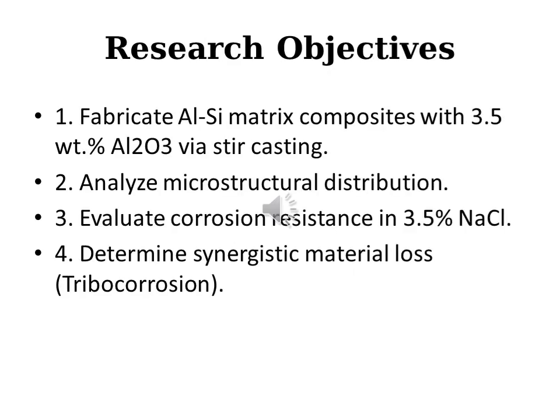Our research objectives are fourfold. First, fabricate these aluminum silicon matrix composites using the stir casting method. Second, to analyze the microstructural distribution of the particles. Third, to evaluate the corrosion resistance in a 3.5% sodium chloride solution. And finally, to determine the synergistic material loss or the tribocorrosion behavior.